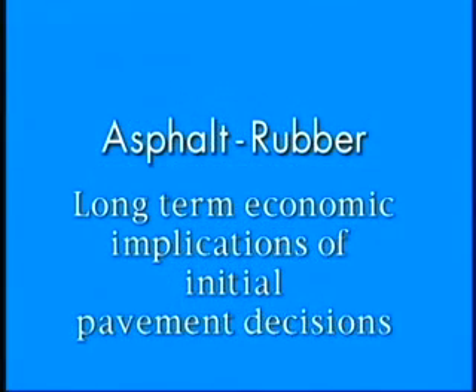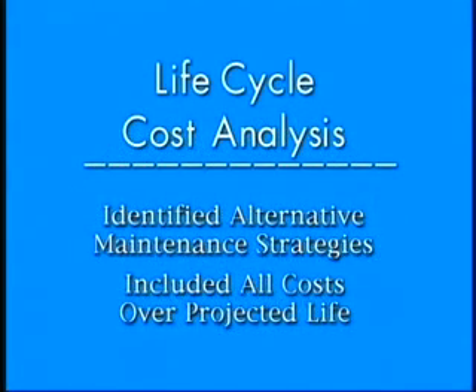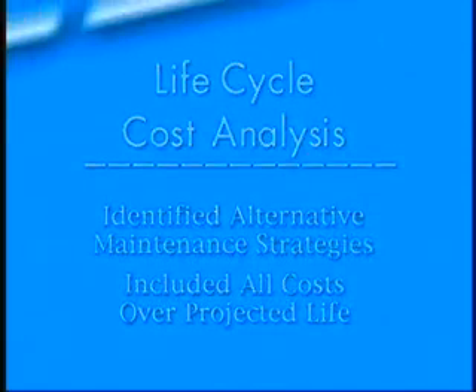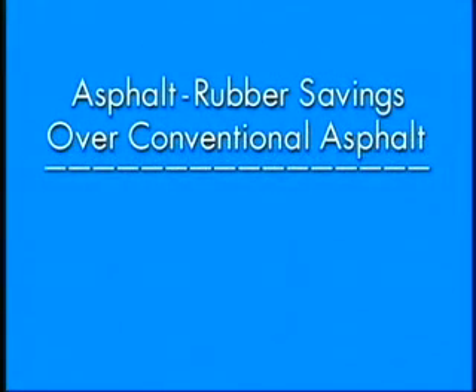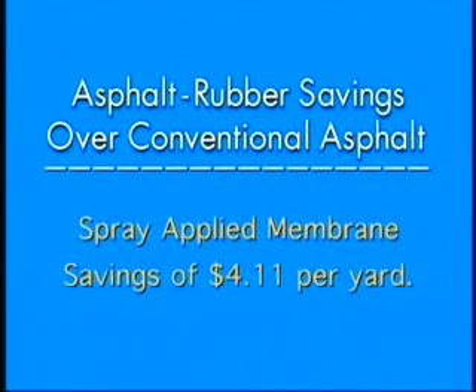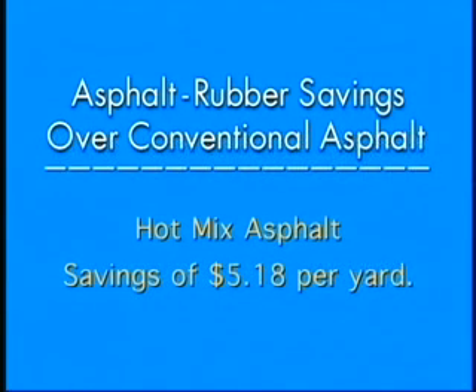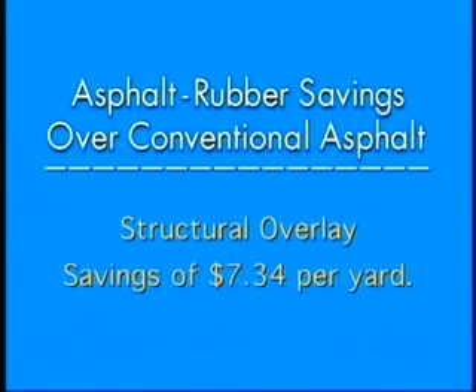Such an analysis was conducted on asphalt rubber to qualify the long-term economic implications of initial pavement decisions. The study identified alternative maintenance and rehabilitation strategies and their expected lives, and included all costs incurred by an agency over the life of the project, from preliminary engineering to future maintenance. Three scenarios used by the California Department of Transportation and their alternatives were examined. With a spray-applied membrane, asphalt rubber produces a savings of $4.11 per yard over conventional asphalt. With a thin hot mix asphalt overlay preservation, the savings for asphalt rubber climb to $5.18 per yard. With a structural overlay, asphalt rubber saves $7.34 per yard over conventional asphalt.